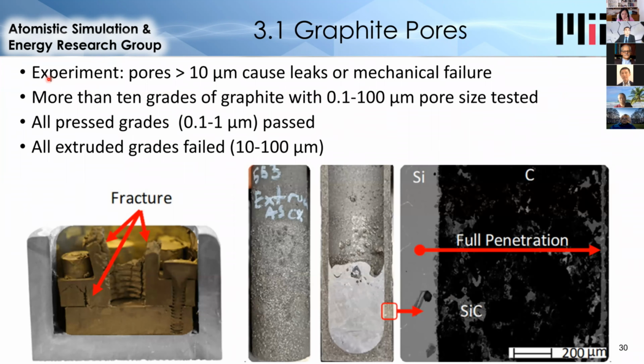So then I ran some experiments to validate this. First, we ran experiments with very low quality graphite, which have large pores greater than 10 microns. And so we expected these to fail or leak, and in fact they did. And these are the figures shown at the bottom here. On the left, you can see a tank that essentially exploded because of the reaction between silicon and graphite. It happened so thoroughly. There are so many large pores that silicon not only leaked through the wall, but also converted so much of the graphite to silicon carbide that the graphite itself broke.